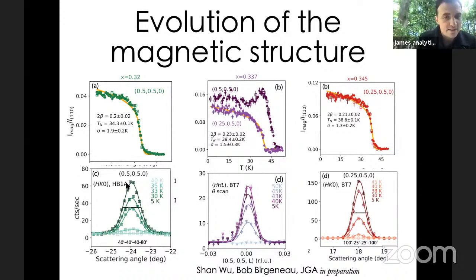What you're looking at here, of course, is just the reciprocal space intensities of the neutron scattering, and as a function of temperature, this is plotting the temperature dependence of that reciprocal space point. And so for the stoichiometric compounds, you seem to see both kinds of magnetic order. So it's a very natural way to explain what we were seeing in the switching. We were seeing switching of one kind with one sign for the underintercalated. We were seeing switching in the opposite direction for the overintercalated. And for the stoichiometric compounds, it seems like these two things basically cancel. And they cancel because both kinds of magnetic order appear to be simultaneously present.